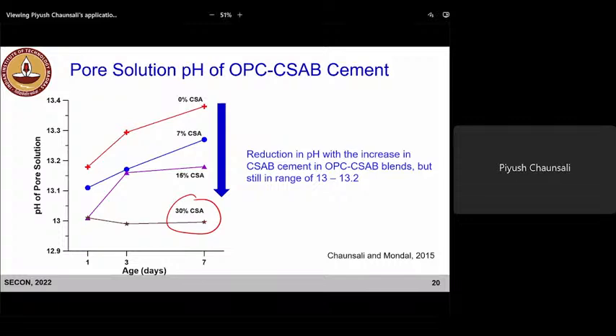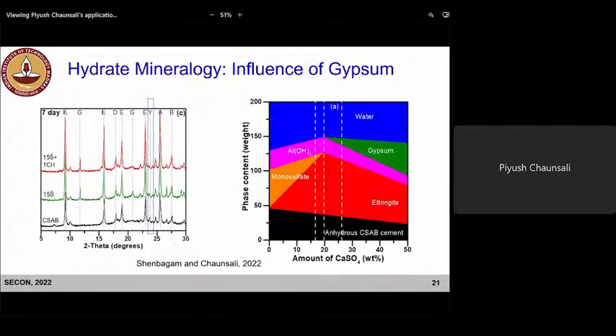Because when we talk about carbonation, right? When the pH is low, becomes 10, 11, then the propensity towards carbonation increases, and carbonation may then induce corrosion. So a lot of work is going on in that direction, where people are looking at the carbonation of CSAB cements, what the propensity of steel corrosion is in these systems, and how we reduce that.